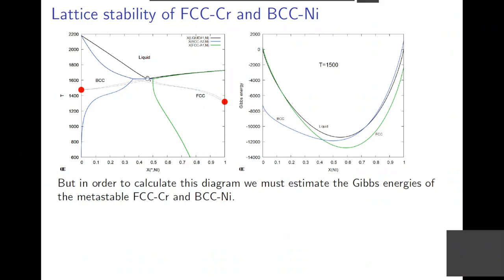And then you can do this kind of extrapolation of the liquidus, solidus for the BCC phase, assuming that nickel is actually BCC, which has never appeared. And that is related to the Gibbs energy curves for the different phases. So I have calculated here Gibbs energy curves at 1500 Kelvin, which is just below the eutectic temperature here. And you have a Gibbs energy curve for the BCC, and this is the stable phase for the chromium side. But on this side, it will be FCC which is stable, but you still need an endpoint of this BCC curve.